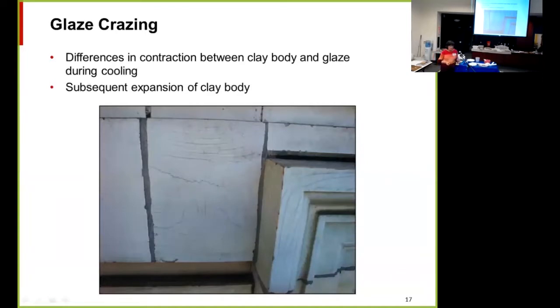Glaze crazing are those fine little cracks that you think of, like you might see on an old Chinese vase antique or something like that. But we also see those on terracotta. And I think those are caused during manufacture by a difference in contraction as the clay and the glaze is cooling. And I've found that they're not usually problematic. I don't usually try and do any repairs to the crazing, because if it's just small, fine cracks like that, you can just let them be. And they're usually so small that water can't really get in there.